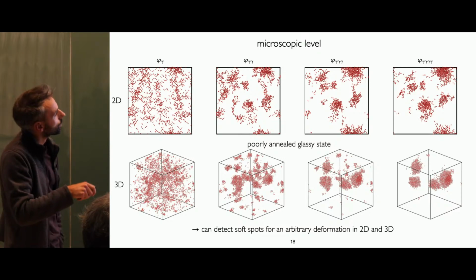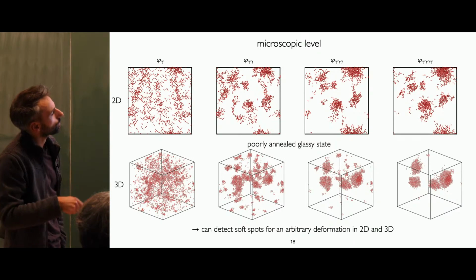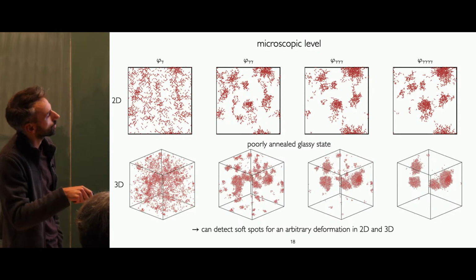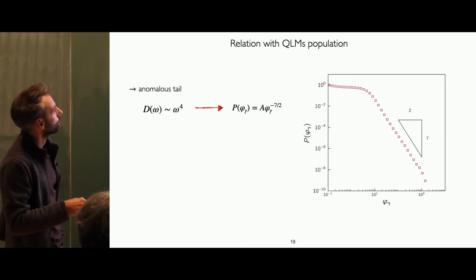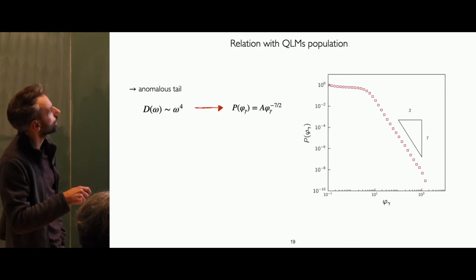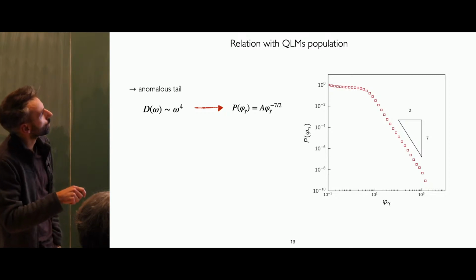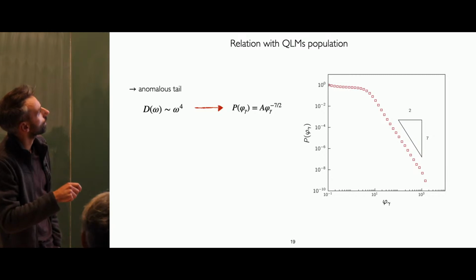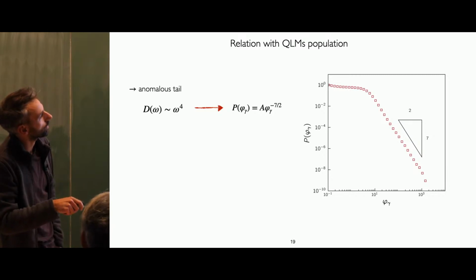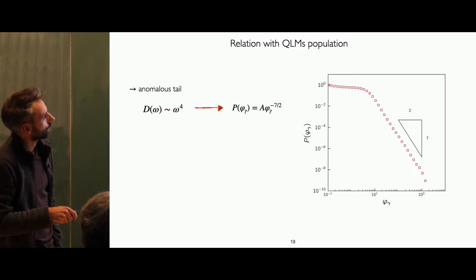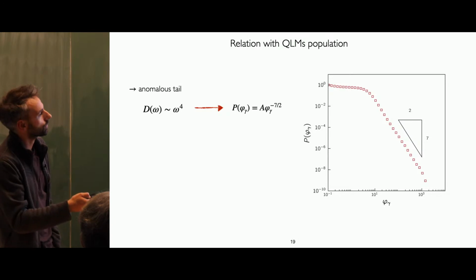So now a quantitative connection, because you see that you have a clear soft spot, so that already gives you an idea that there might be some soft mode underlying that couples with this deformation. And we can actually make a formal analogy where we know that from the structure of this coefficient, for example, I take the first one, if the density of states will scale as omega to the 4, we will expect that there will be a large variation of bonds that have a coefficient that decays as a power 7. So those anomalous tails are like telling you about defects in your system,